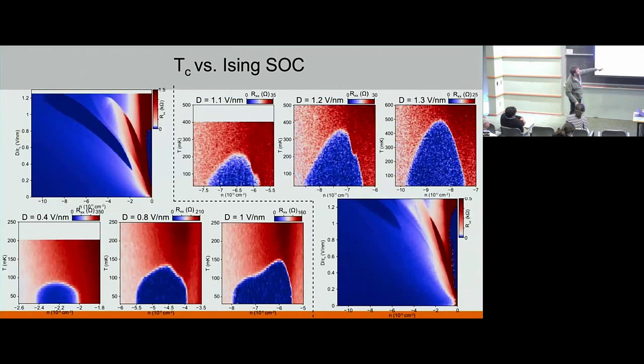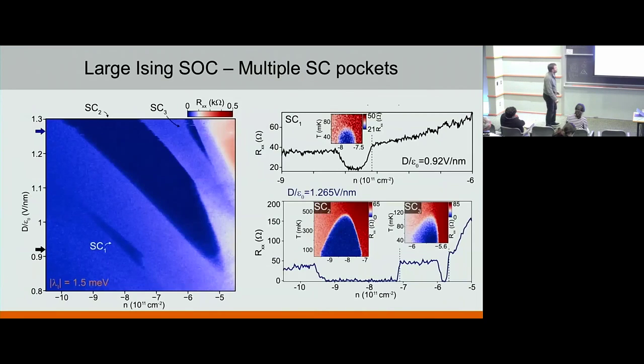So the reason why we are focusing on this case is that, here it's maybe not super obvious, but instead of having just one pocket of superconductivity, which we have for this small Ising, we actually have multiple superconducting pockets in case of large Ising. And in total, we found 3 superconducting pockets. These are SC1, SC2, and SC3. Everything I told you so far is SC2 here. That's the biggest, most dominant pocket. SC1 was discovered here at UCSB by us sending samples to Andrea, where he figured out that in one of the samples he can measure this SC1. And then SC3 was discovered by us systematically searching for these effects.